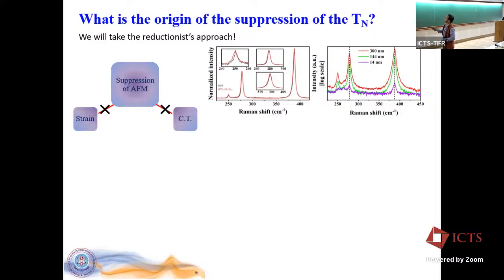So strain we rule out, because if there is a strain, then we should be able to see a signature in the phonon frequency shifts, which is what is missing in our cases. As you can see in the data, we don't see any change in the frequency values irrespective of the thickness. If there is a strain, it will be maximum for thinner samples and will reduce as we go thicker and thicker, and therefore we should be able to see a change in the phonon frequencies, which would tell us whether there is strain or not.